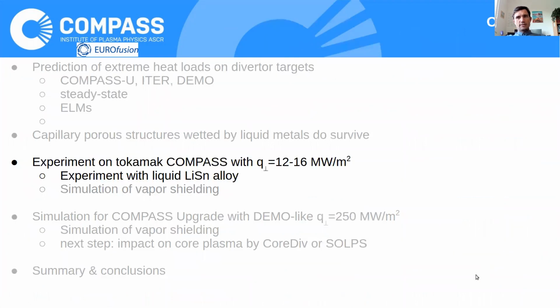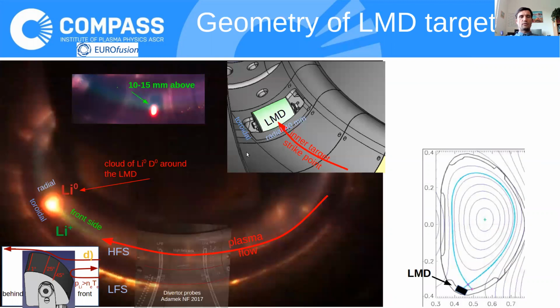Right. Let's go to the experiment on tokamak COMPASS, where we expose it to these high heat fluxes. So here you can see the geometry. This is tokamak COMPASS with a major radius of 0.55 meters, and we put the liquid metal divertor target at the inner strike point, placed such that there is a high incidence angle, so that when we insert it a bit deeper into the plasma by a couple of millimeters, the angle of attack goes nearly to 45 degrees, so the heat flux gets very high. Here you can see how the plasma flew above our divertor probes, which measure the parameters of the incident plasma, including ELMs, because they have a time resolution of 1 microsecond and 3 millimeters in space.